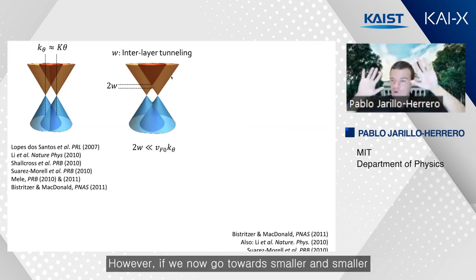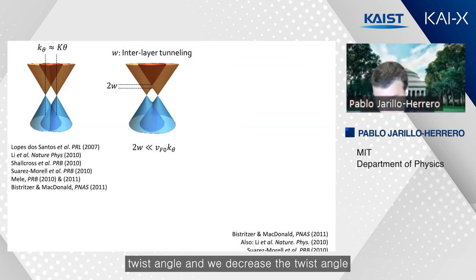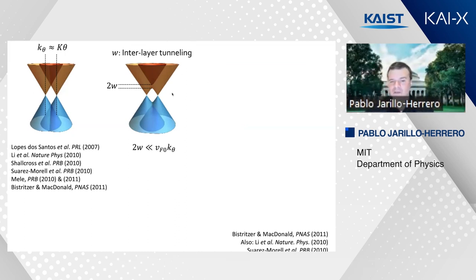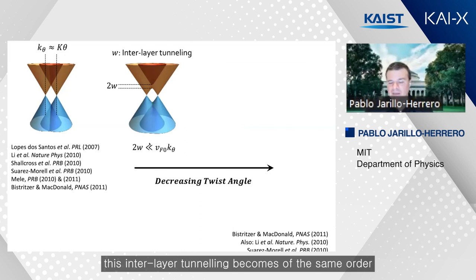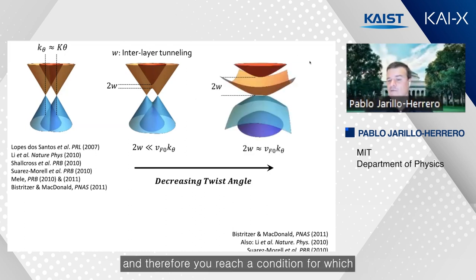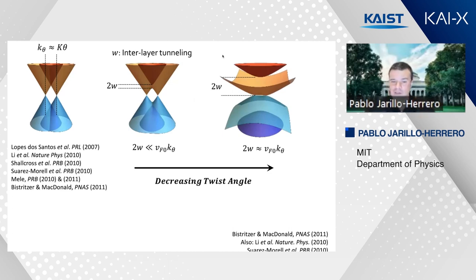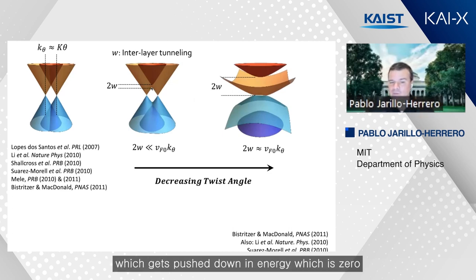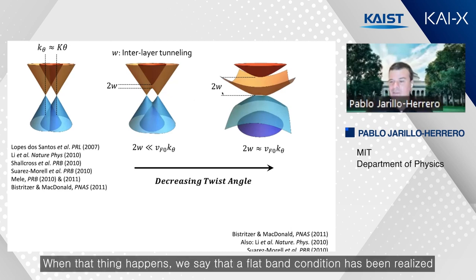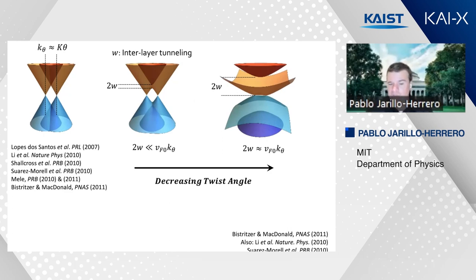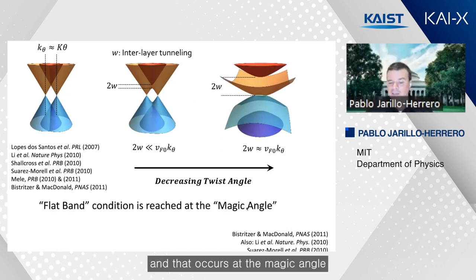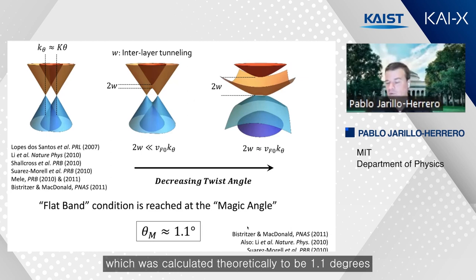However, if we go towards smaller and smaller twist angles, then this interlayer tunneling becomes of the same order as the energy of this crossing point, and therefore you reach a condition for which this lower band, which gets pushed down in energy, reaches zero. When that happens, we say that a flat band condition has been realized, and that occurs at the magic angle, which was calculated theoretically to be 1.1 degrees.